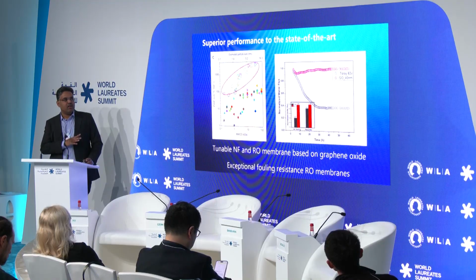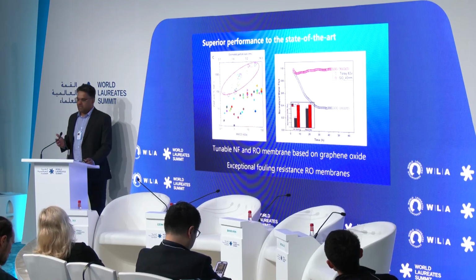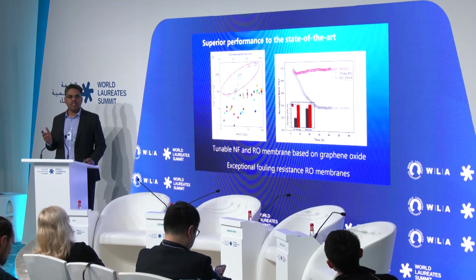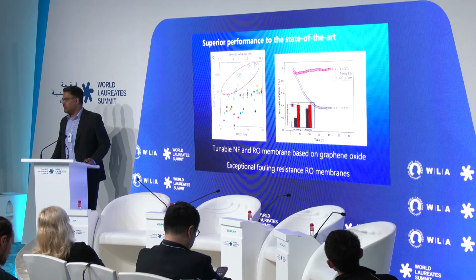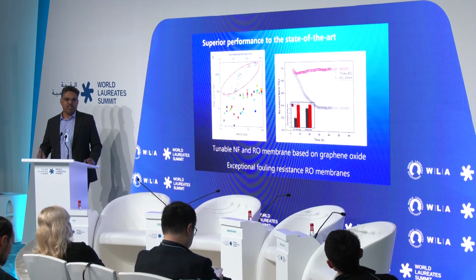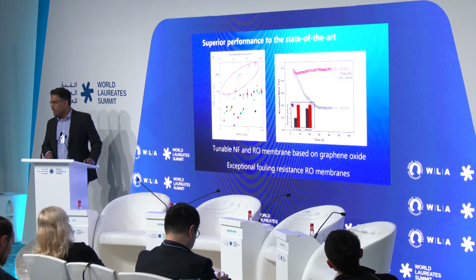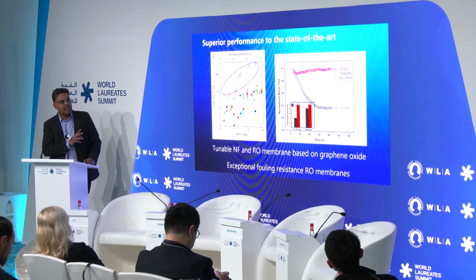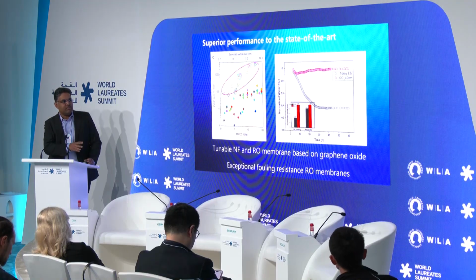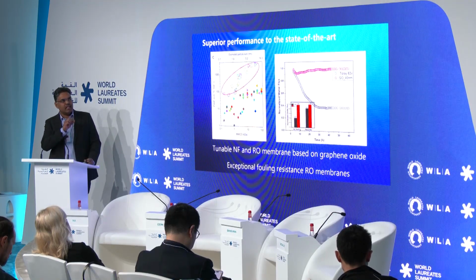That data is specifically on fouling, which is a technical term in water filtration. Salt rejection is 99.9% even with the commercial membrane, and graphene can get the same. But the real benefit is in the lifetime of the membrane. It is called membrane fouling, and this data is from biofouling. If you look at the membrane performance as a function of time, the Toray membrane decreases in water flux with time, but with graphene, yes, there is a slight decrease, but it stays there. It is mainly because it has a self-cleaning capability, so the foulant does not stick to the surface. Because of the cross flow, water flowing through the membrane keeps the membrane surface cleaner. That means we can extend the lifetime.